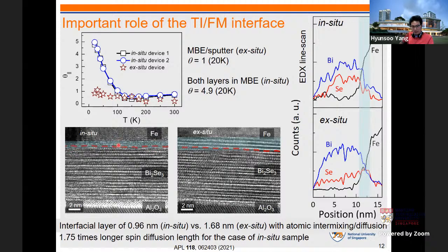And we found this intermixing thickness is 0.96 in case of in situ method, but ex situ we found is about 1.68, about 2 times thicker. So we will have more intermixing and diffusion in case of ex situ, which is also supported by this EDX scanning. And you can see basically there is more diffusion of selenium into these interfaces. So basically, we identify 3 roles of these scattered spin Hall angle values from topological insulators.